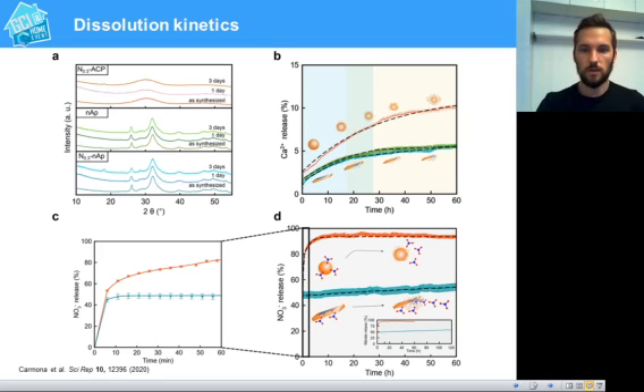We can see a burst effect of nitrate release that is probably due to nitrate loosely bound at the surface, but after that a very slow and controlled release is matching the calcium release at a longer time with the same kinetics. And this can be interpreted as indicative of a slow nitrate release that is paired with the dissolution of the particle. And this is a major hint of nitrate incorporation within the crystal lattice.